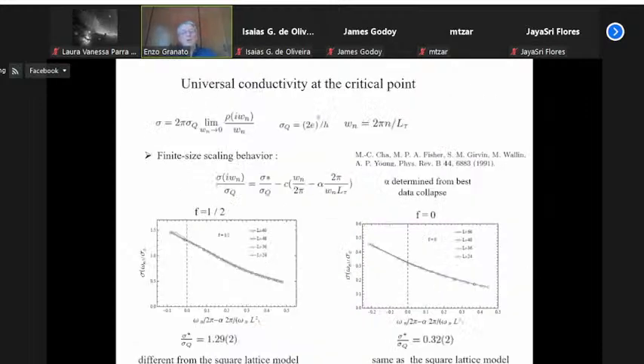One can also calculate the universal conductivity at the critical point. The conductivity is related to the phase stiffness, and you have to take into account that the system is finite, so they use a finite size scaling to extrapolate to the zero frequency limit. This has been explained in this paper in detail. And when you analyze the data, you find that the conductivity at the transition